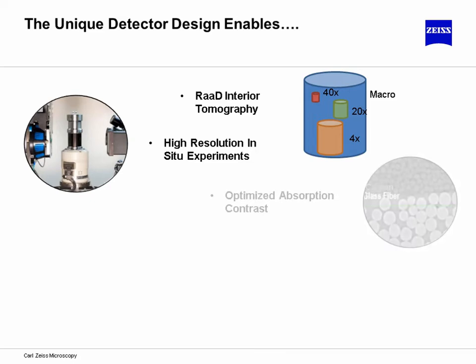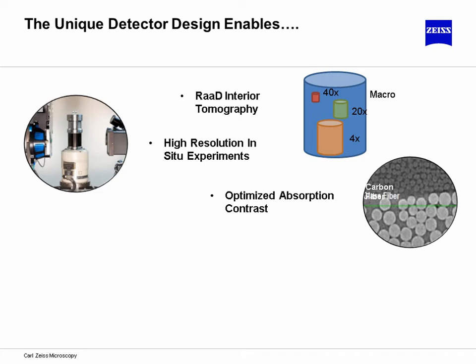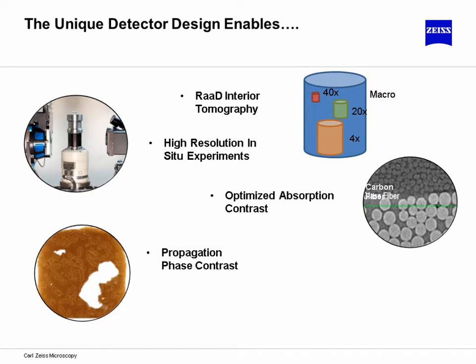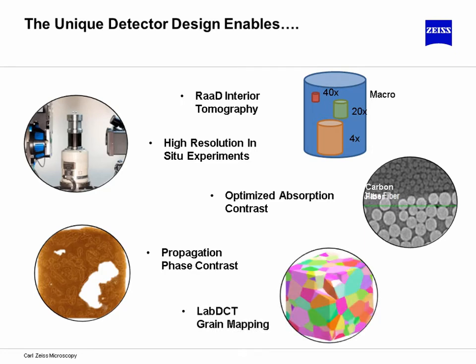Of course, the ability to look at samples in their natural environments in situ stages, such as this tensile stage here from Deben, which was placed here into the Versa microscope. Looking at optimized absorption contrast is a key feature, and this has to do with the efficient use of scintillation material and coupling to the optical system. A unique phase contrast, propagation phase contrast mechanism, which allows to extend another contrast mechanism beyond pure absorption, which gives you density. Phase propagation allows you to detect features which would otherwise not be detectable.